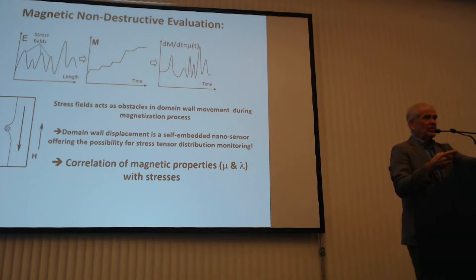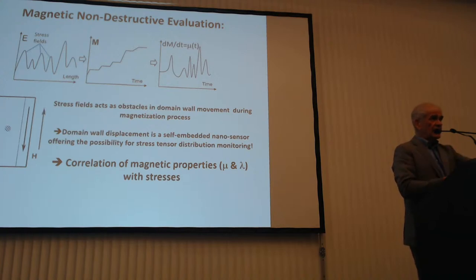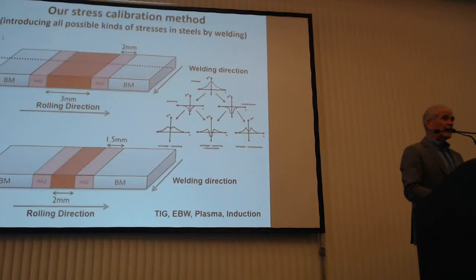since their movement, let's say, is the main mechanism of the magnetization process. And in the presence of any defect, you can detect such a defect by the magnetization process. So, what we have done is that we have developed certain coupons made of autogenously welded steel samples, of different actual samples, and therefore we generated different levels of residual stresses there.